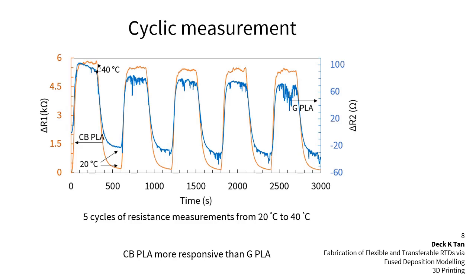The results showed that the carbon black PLA temperature sensor was more reliable and stable than the graphene PLA sensors. The resistance of the graphene PLA sensor did not return to the value when it was first measured at the end of the cycle, and there were some small fluctuations during the measurements. The change in resistance of the graphene PLA seems to have experienced a lag as the temperature changed, whereas the response of carbon black PLA seems to be quicker than the graphene.